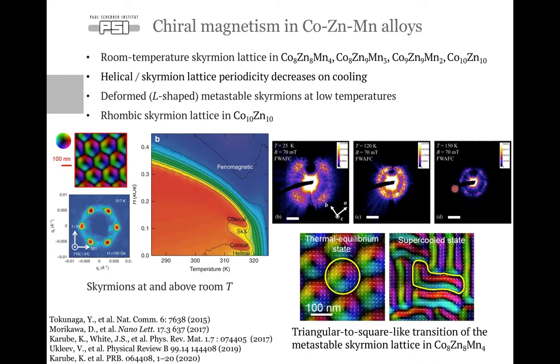Thus, from room temperature down to around 150 K, we have a triangular or hexagonal skyrmion lattice that is typical for B20 materials and other kinds of cubic chiral magnets. But as we cool down, we get into the so-called amorphous skyrmion state, where the skyrmion lattice is orientationally disordered, and eventually we have a deformed or square-like skyrmion lattice at low temperatures. And this has been observed in both neutron scattering from bulk samples, but also resonant X-ray scattering and Lorentz transmission microscopy in real space.